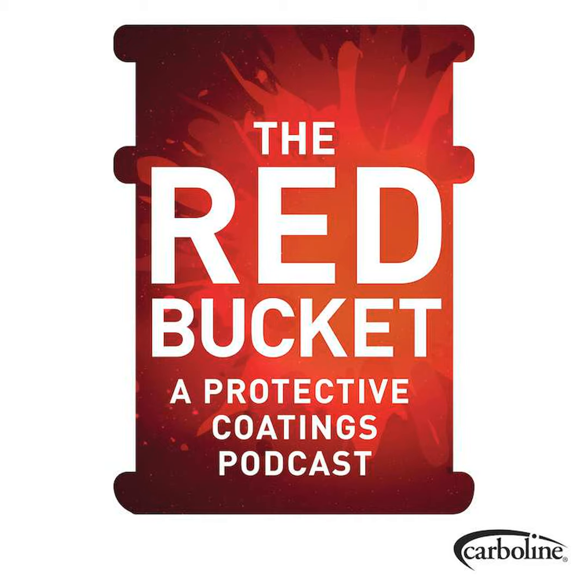So the more UV light that hits that epoxy, that starts breaking down. And then eventually you'll get that moisture into your primer, and you'll start going through the zinc if you're using a zinc-rich primer. So the shell or the top coat is really more than just aesthetics. It really is a protective layer that protects all the layers underneath and allows them to do that job. Just like you mentioned with the weather-resistant siding on the house.